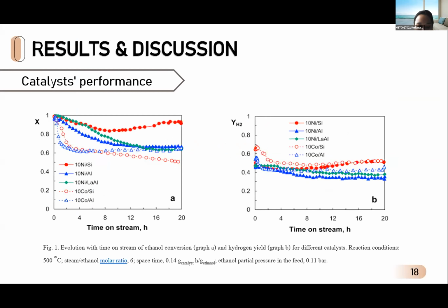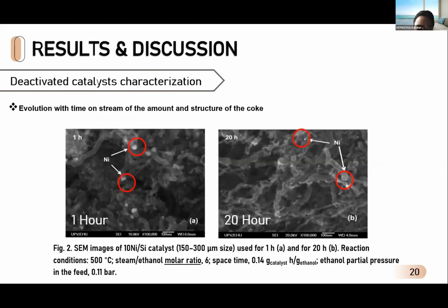First, figure 1 shows the evolution with time on stream of ethanol conversion and hydrogen yield for the different catalysts in the ethanol steam reforming at 500 degrees Celsius, steam to ethanol molar ratio of 6, space time of 0.14 gram catalyst hour per gram ethanol, and ethanol partial pressure of 0.11 bar. Figure 2 shows the SEM image of the nickel particle.